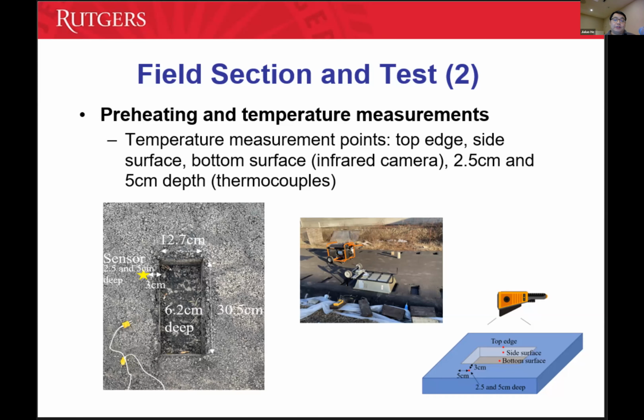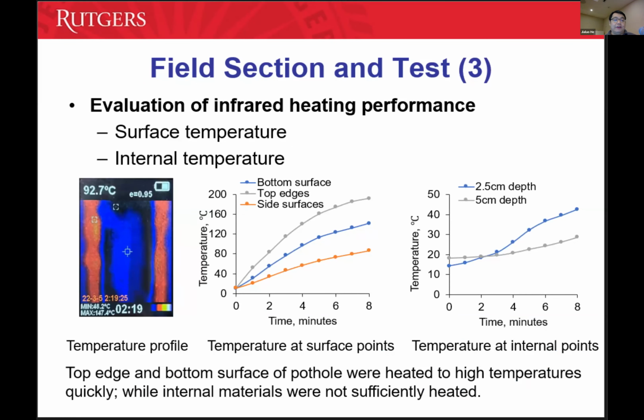We also have thermocouples embedded during construction at different depths, so we are able to get the temperature inside the pavement while we do preheating. We also use a thermal camera to quickly get the temperature on the surface. Here is one of the measurements we have. The left one is from the thermal camera, the infrared camera, so you quickly get the surface temperature. You can see that within a few minutes the temperature increases pretty quickly, compared to the right one, which is captured by the thermocouple. There the temperature still increases, but much more slowly.